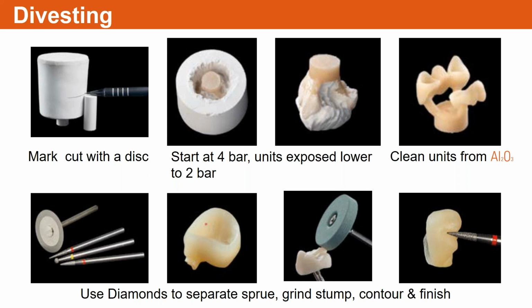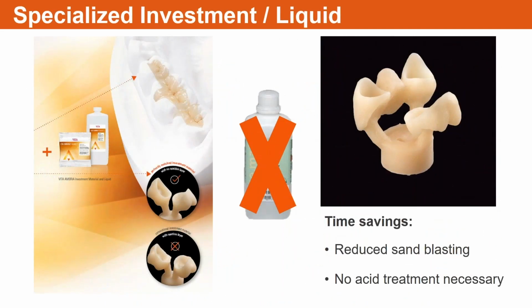If you try to sandblast this at too high of a pressure, you will cause damage, pitting to those restorations. So you've got to make sure you lower that pressure. Now, once you've divested it, you're going to remove it, clean it up, and then just use diamond instruments, just like you do traditionally, to contour it, to finish it up.